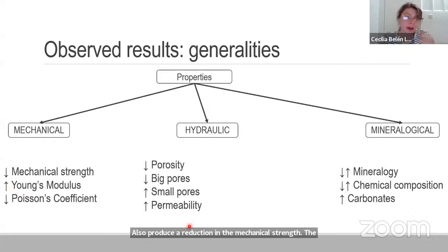What we believe, I say believe because we haven't yet confirmed it, is that the reason why the permeability is increasing is that during this fines migration and during the carbonation process, the rock is suffering some type of cracking, which would increase the permeability.